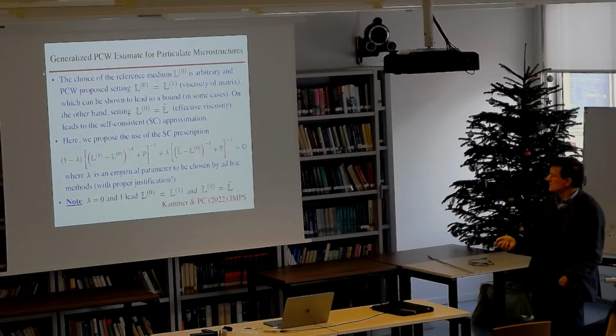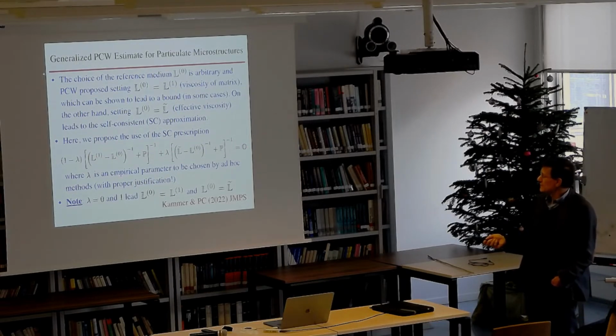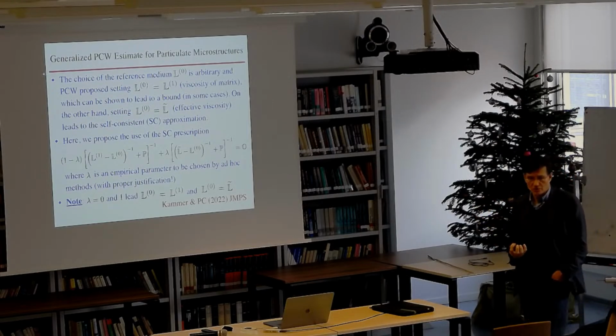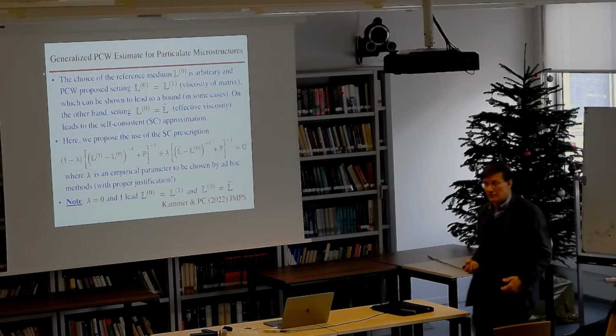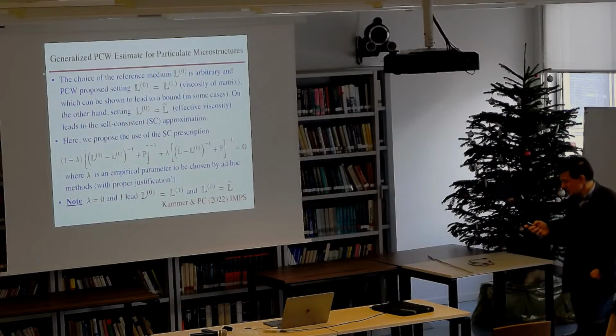We proposed this use of a self-consistent prescription interpolating between L1 and L tilde. This is the self-consistent equation for a two-phase medium with properties L1 and L tilde. But now there's a parameter lambda, it's not a volume fraction anymore. This is the interpolating parameter that tries to give you information on this additional microstructural variable that we cannot extract directly from these Hashin-Shtrikman type variational principles.